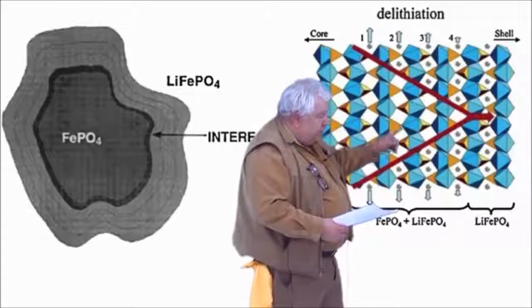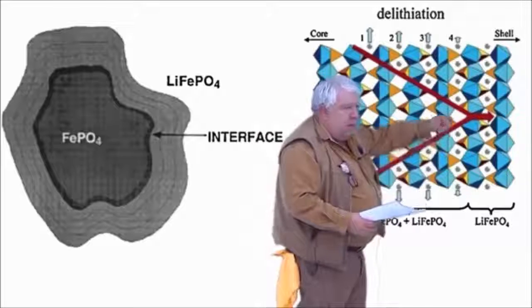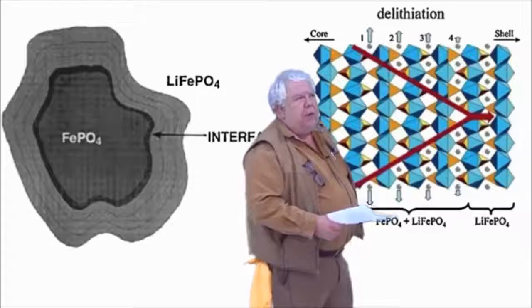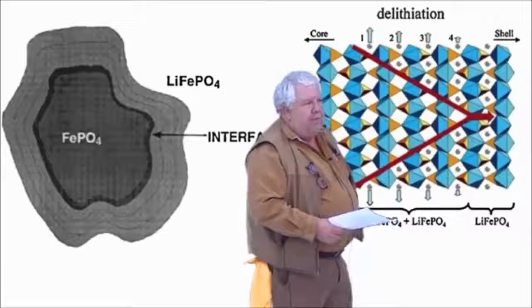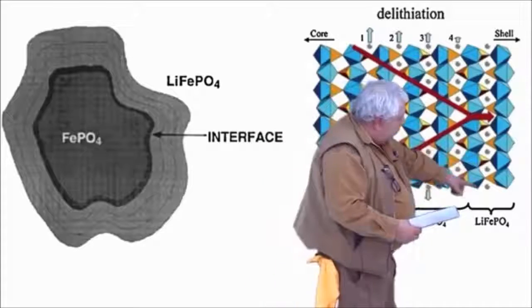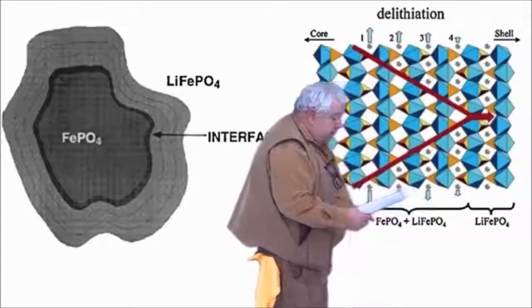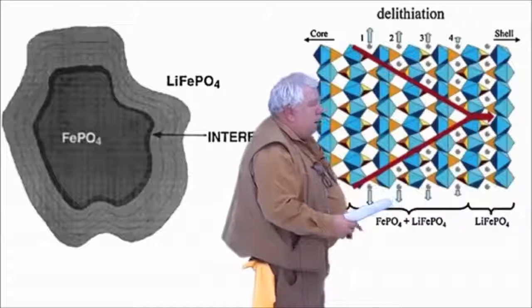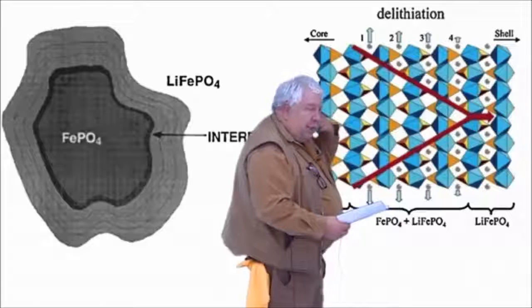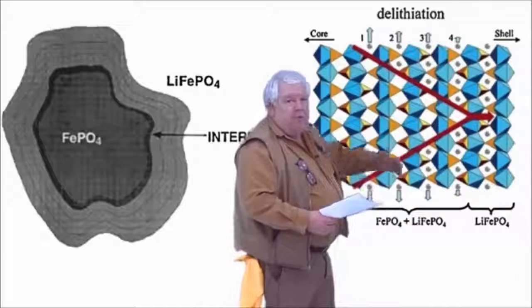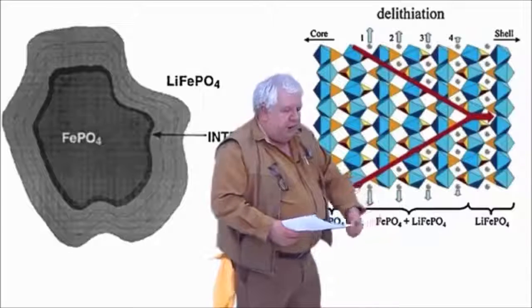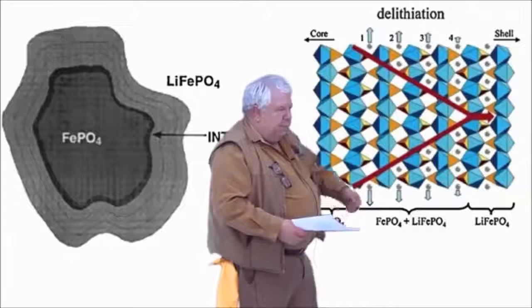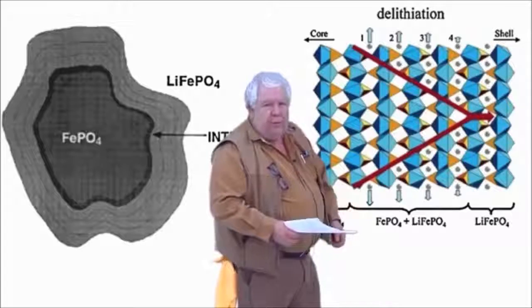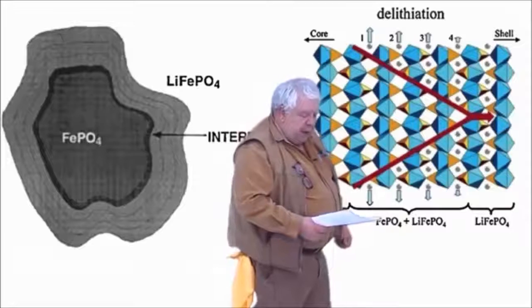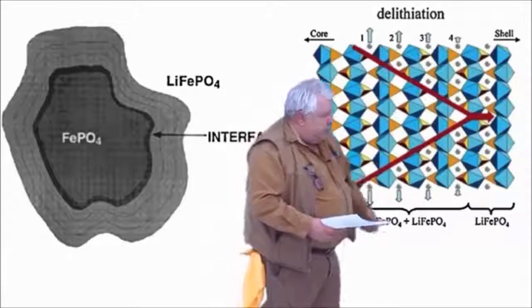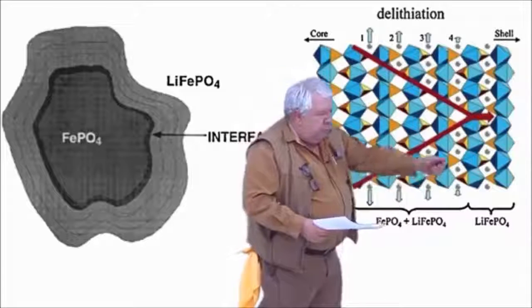But there is a difference on this end. These channels are very narrow. And so we think of that as, they call it, a domino effect. If you add an electron in here at the bottom, anywhere in here, it has to move up. All the lithium ions in front of it have to move ahead one position. And they are positions, kind of like dimples in the Chinese checkers board, or BBs in the little toy where you have to put all the BBs in the right place. They lock into these positions, and then if you shove another one in behind, it'll move the ones ahead up.